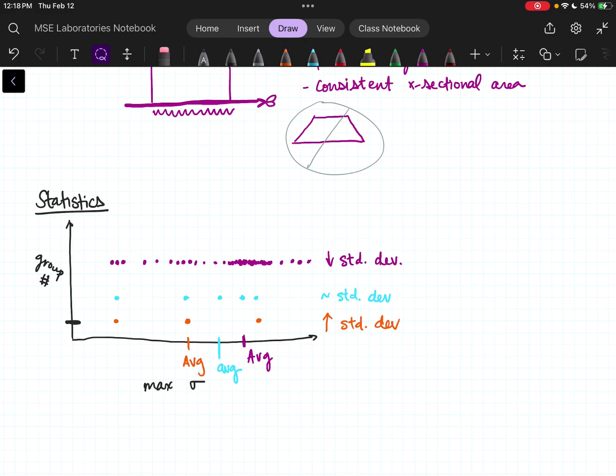Really generally, the more data you collect of the exact same thing over and over, the more you can trust it. So this orange one, I can't trust this value. It has a really high standard deviation. The blue one, I can trust a little better because it's getting a little closer to the true values. But if on this blue one I had gotten one random hit way up here, that would have thrown my average way higher, for one data point. Ideally, if I collect one outlier, it should not drag my average way higher or way lower.